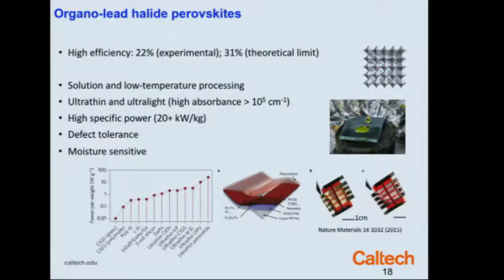This is not an oxide perovskite that is familiar to many of you. It is a perovskite crystal structure, but one which has halogens like iodine rather than oxygen on the perovskite octahedral lattice. And it has typically organic cations, and then uses something like lead as the center B atom in the ABO3 crystal structure.